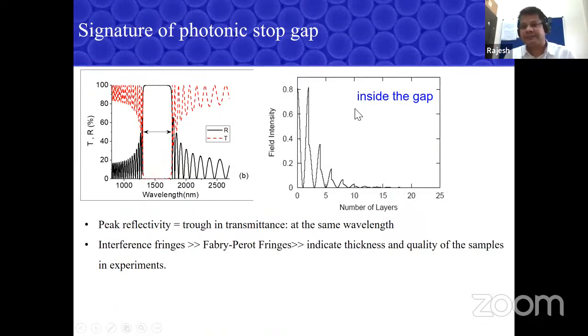How do you know, if I give you a sample, whether it has a band gap for light or not? Experimentally, you have to measure the reflectivity and transmission of the light as a function of wavelength. You can see the calculated reflectivity spectra for these 1D samples. There is a peak in reflectivity, around 100%, and at the same wavelength you have 0% transmission of light. That means the wavelengths which fall within this range do not propagate through the system.